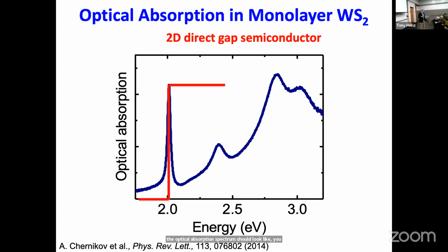And a lot of the 2D materials like quantum wells that are, we would say, more quasi-2D, thicker, but the electrons are confined, actually look quite a bit like this. So you would have to say this is not very good agreement. What's missing from this? Well, this is a correct description of uncorrelated transitions for uncorrelated electrons, where the states basically look like Bloch waves of the electrons and holes. But in fact, you expect to have interactions between the electron and the hole. That's an excitonic correction. Typically, that's fairly weak in bulk materials.